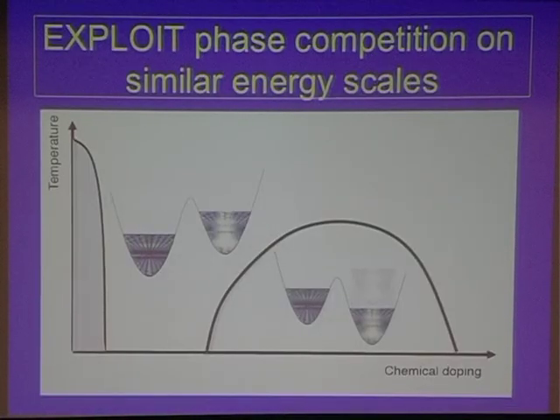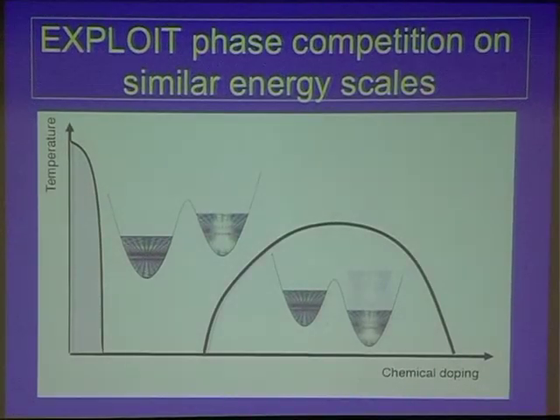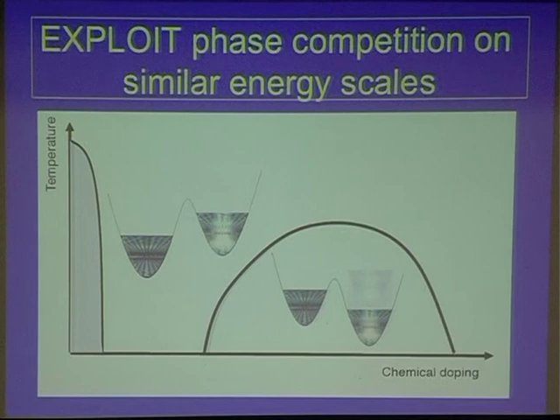So the idea behind this is to exploit the phase competition on similar energy scales that I have repeatedly emphasized to our advantage. This competition comes from the fact that we have two different states of the system, and the energy difference between these two states is quite small, so that small perturbations can switch from one phase to the other. This is often a complication because this phase diagram as a result has many, many different phases. But perhaps if we can control and trigger the material to sit there when actually in real life, in equilibrium, you would like to sit here, we can perhaps exploit the functionality of this state, which may be more interesting than this one. So this is the idea.